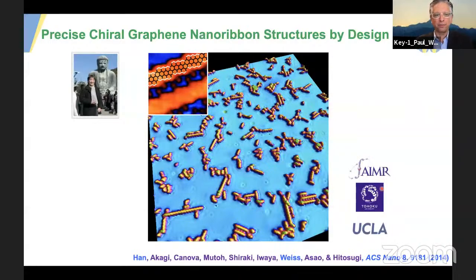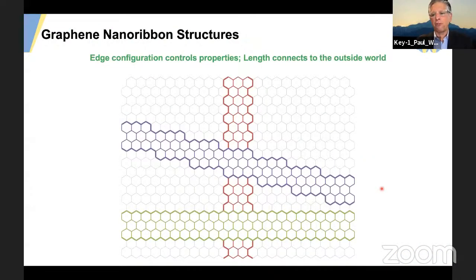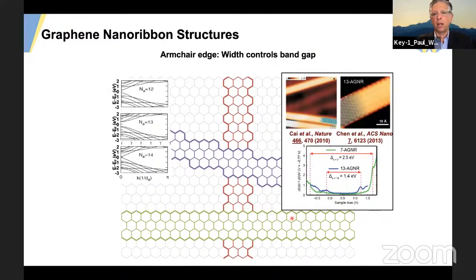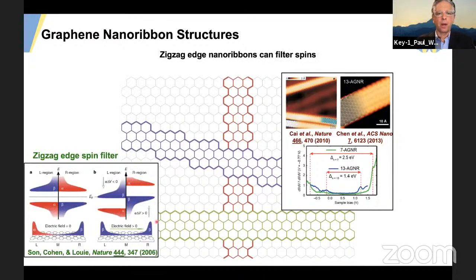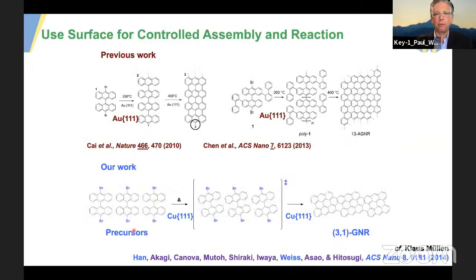Okay, so Patrick's particular interest was to explore chiral graphene nanoribbons, thinking that the armchair and zigzag edges had already been explored quite a bit. So the armchair, you might remember, as one goes from the semi-infinite planes to narrower segments, goes from 0 band gap to increasing band gap with narrower chains. The zigzag nanoribbons have interesting spin properties along the edges that different groups have been exploring.